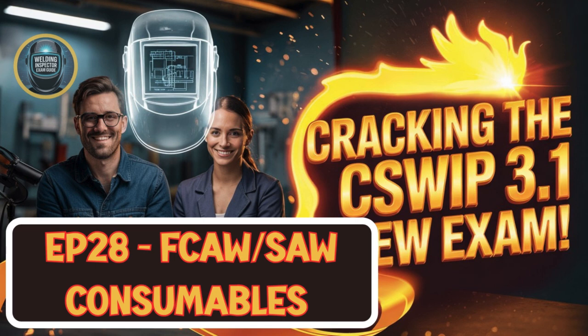That's the core trade-off. Their big advantages include the easy addition of deoxidizers and alloying elements, giving you really precise control over weld properties. They can also generally be used with thicker layers of flux during welding. The disadvantages, though, are pretty significant. As we touched on, they have a strong tendency to absorb moisture. This is a big one.